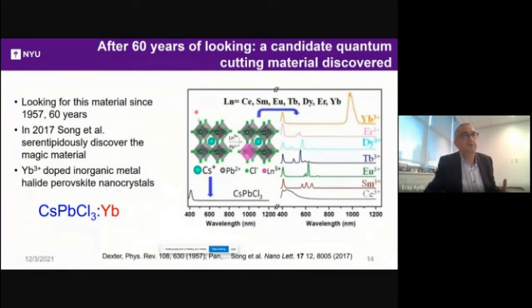People looked for it for 60 years, and finally, people discovered a candidate by accident. Okay, so in 2017, a group in China, Song et al., accidentally discovered this magic material, and the magic material is cesium lead chloride, a halide perovskite that is doped with ytterbium, and they discovered it in nanocrystals. I'm going to show you that it doesn't have to be nanocrystals, but the ytterbium is important. And so here, what they were doing was essentially taking halide perovskites, the hottest material, so there's a lot of papers being written, and they decided to put all the rare earths into the cesium lead chloride and see what happens.